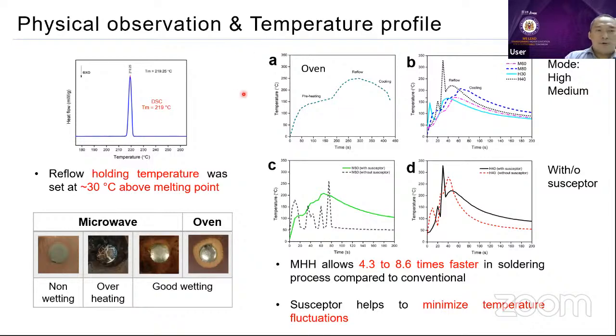This one is the result from the oven, right? The highest is 250. We need to go a little higher than the normal temperature to make sure everything melts before we stop the run. Then we compare. This one is for the microwave, for the medium mode and then the high mode. So we compare both of them. If we use the high mode, we can reach about 250.